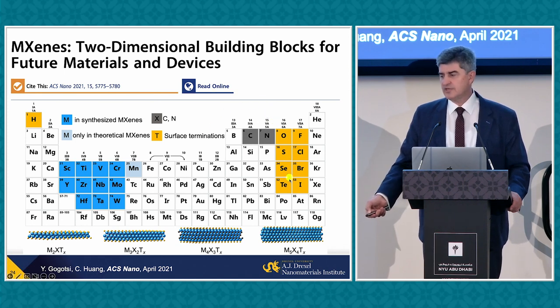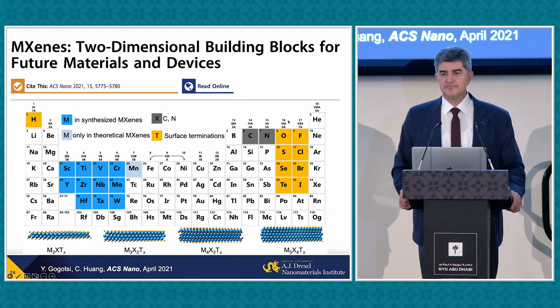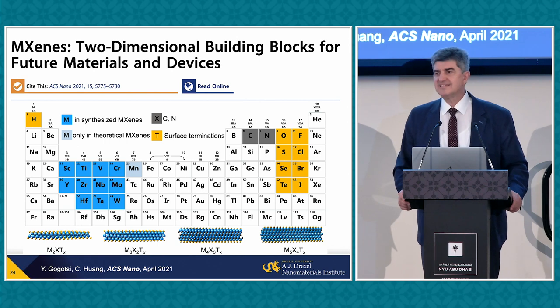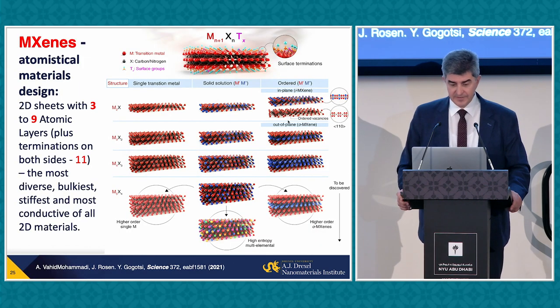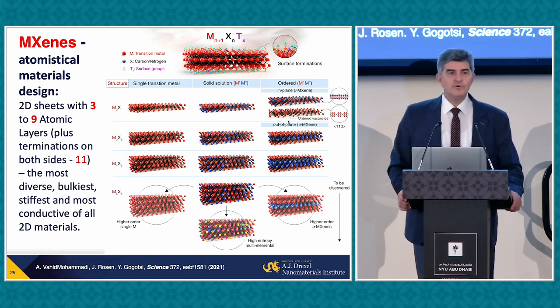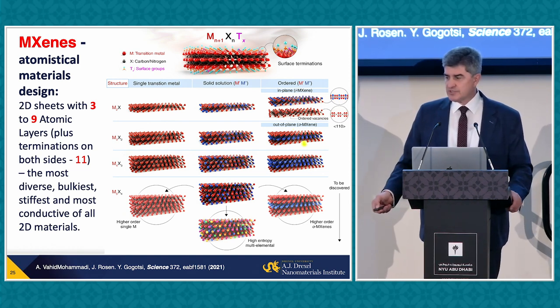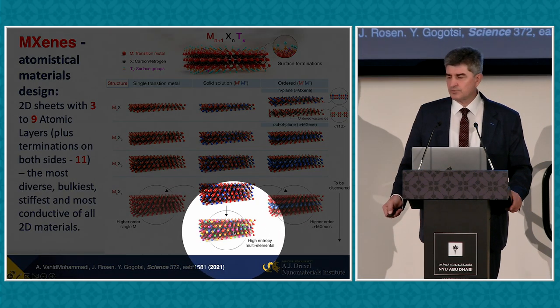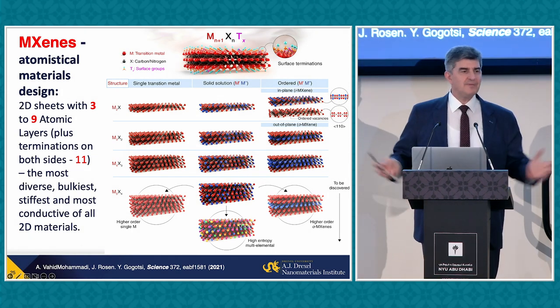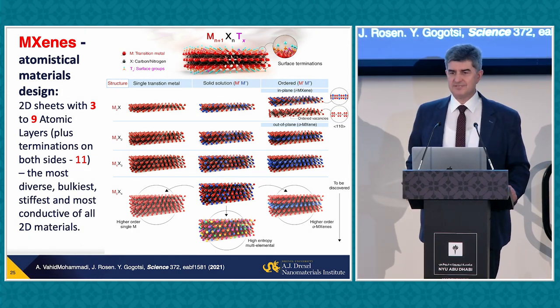Oxygen, hydroxyl, chalcogens, halogens, amines. Multiply by 10, you end up with about 1,000 possible stoichiometric compositions only. But we can also mix and match transition metals, making solid solutions on the M side, like alloys, actually also making high entropy materials, where we have 4 to 5 elements mixed together. We can also make carbon nitrides, mixing carbon and nitrogen. By itself, that takes the number to basically infinity of possible compositions.